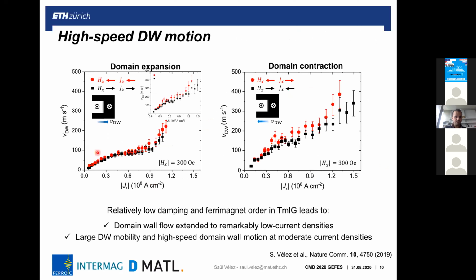And last, I'm showing here the domain wall velocity. We can drive domain walls at quite low current densities, at which typically in ferromagnetic layers such as cobalt or cobalt iron boron you cannot drive the domain walls. We can drive them in the range of 100 or 200 meters per second, which tells us that these materials are ideal for racetrack memories.